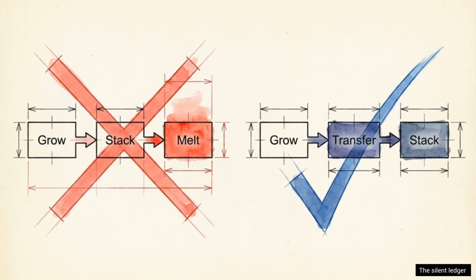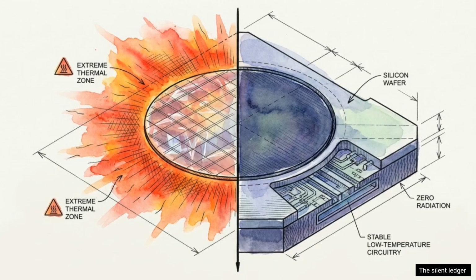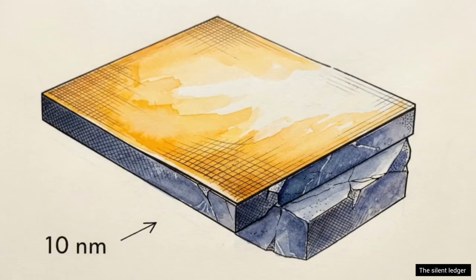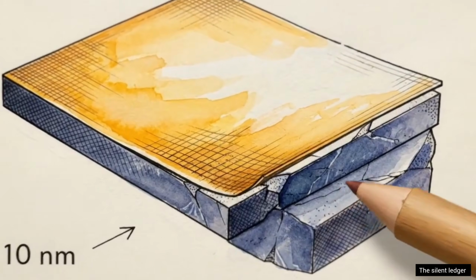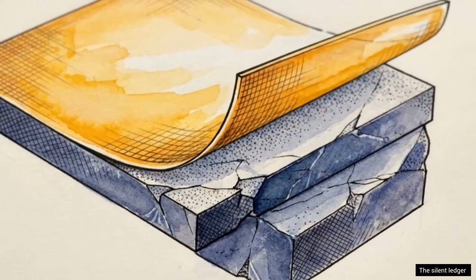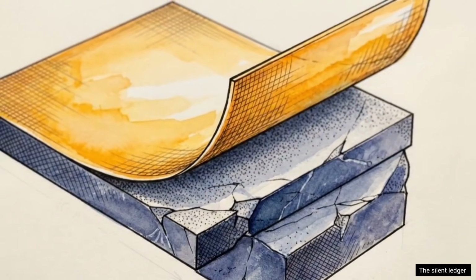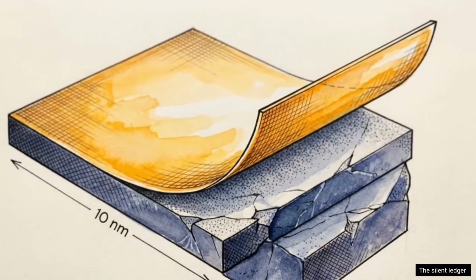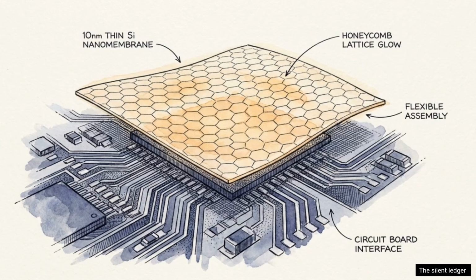A breakthrough from the University of Illinois bypasses this thermal paradox by changing the fabrication sequence. They realized that high-temperature processing is only required to grow high-quality silicon. It is not required to stack it. Instead of growing silicon on top of a finished chip, they prefabricate single-crystalline silicon nanomembranes. These are sheets 10 nanometers thick or less that already possess perfect crystalline structure before they touch the actual circuit.